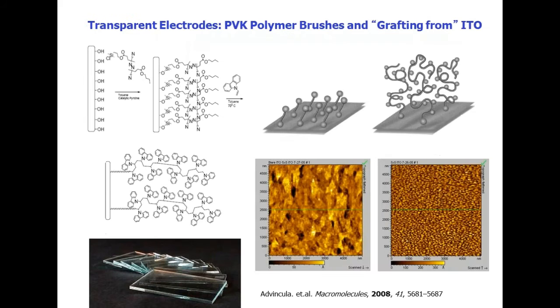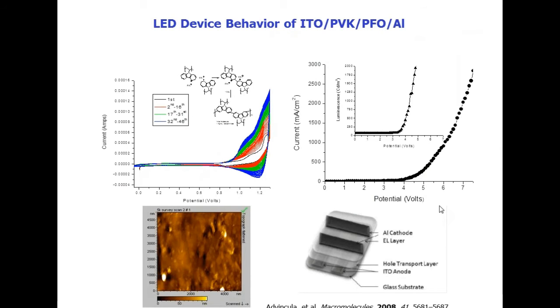On the other hand, we've successfully grafted polymer brushes on indium tin oxide so that we can utilize them for efficient LED devices, ITO being a very useful transparent electrode in many smartphones or display devices. In this case, you can see that AFM was used very well in differentiating that of a rough ITO surface, and then after functionalizing it with the polymer brush, we homogeneously covered the roughness and at the same time improved the performance of ITO, as shown in this current to voltage performance, where we not only lowered the turn-on voltage, but we also improved the stability of the device.